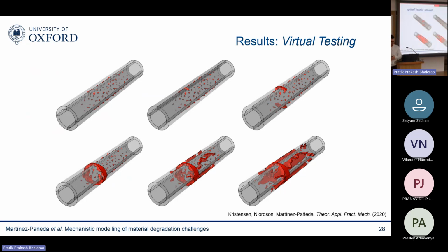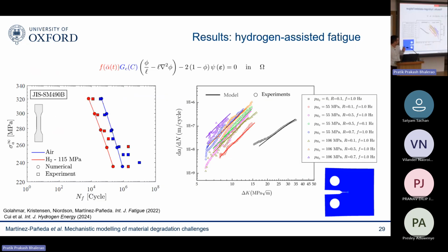This is the takeaway. And we have extended this to fatigue. Here what you have is basically a fatigue degradation law that reduces your fracture energy, and we use this to obtain SN curves and also fatigue crack growth rates, Paris law type of behavior. And I think the beauty of this is that this is work that we did with one of our industrial partners, Tenaris, and